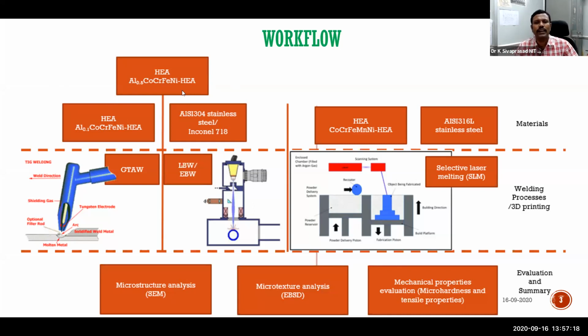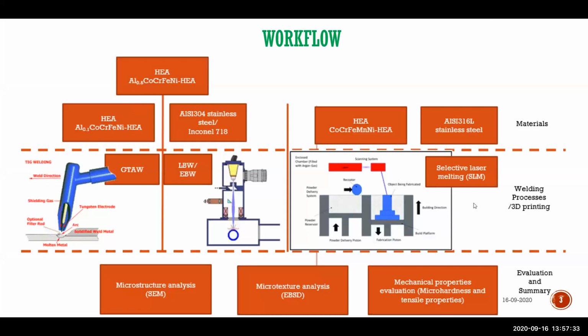Aluminum, cobalt, chromium, iron, nickel: initially one of the other MTech students worked on it. But if you add full aluminum, it will become BCC. BCC is relatively brittle, and we felt that it is less weldable. Then the moment we started reducing the aluminum fraction.